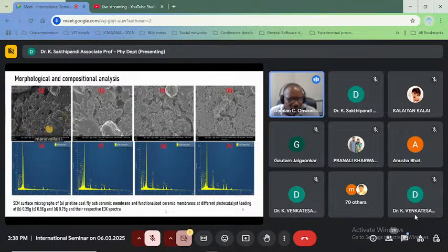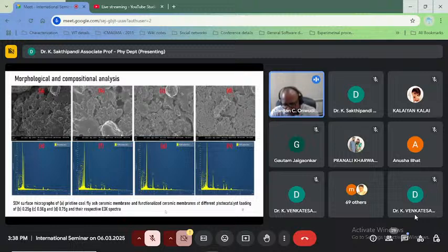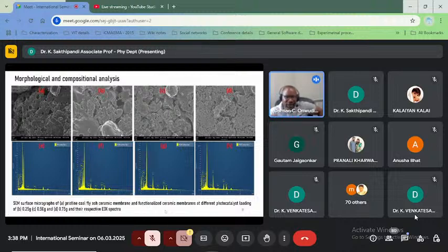We also used EDX to confirm that this material contains the membrane as well as the nanoparticle. In this case, the nanoparticle we used was zinc oxide coupled with titanium oxide to form a heterojunction. Why? We also wanted to reduce the recombination process in the nanoparticle. So we combined two materials together to address the problem of recombination in photocatalysis, which is a very huge challenge in photocatalysis. So we are able to address the problem of photocatalysis as well as the problem of the ceramic membrane. Next slide.